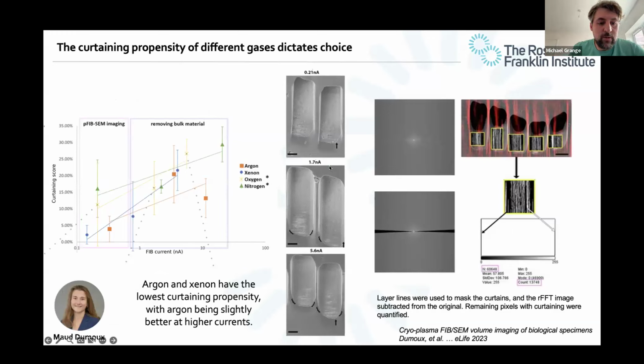Here, what you do is you do a Fourier transform of the surface, and then you look for the layer lines, and then you segment those layer lines out and remove the rest. Then what you essentially have is a plot of all the lines that are on the surface of that face. And we can then plot a curtaining score based on the number of lines, and then plot that as a function of current to see what propensity different gases have at different currents, for example.